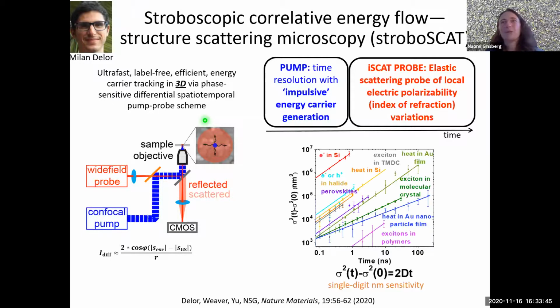It works for a really wide range of materials, some of which are plotted here, and especially over a very large dynamic range in space and time. And from this, we can compute a diffusivity from the data with sensitivities based on the fact that it's shot noise limited to very, very small, say, nanometer changes in the extent of a distribution.